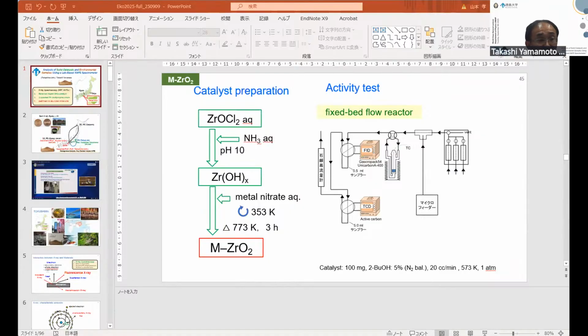These are the procedures of catalyst preparation. Firstly, we prepared a zirconium salt and hydrolyzed it to make amorphous hydroxide. This has a very, very large surface area, maybe 300 square meters per gram. After that, we add the metal source to this amorphous hydroxide and calcine. This is a very simple sample preparation procedure: a large surface area hydroxide is first prepared, and the metal source is incorporated and calcined. The catalyst activity test uses fixed-bed flow reactors like this.